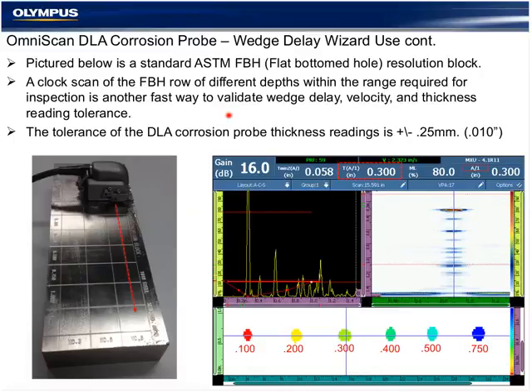In this case, the A-scan is fixed, but I could put it in track mode and slowly walk it across the same calibration standard for a validation of each A-scan on each flat-bottomed hole for a validation of the thickness measurements.